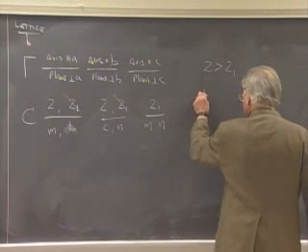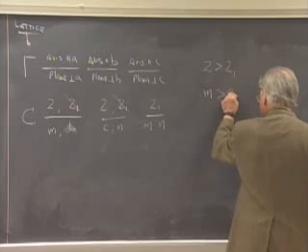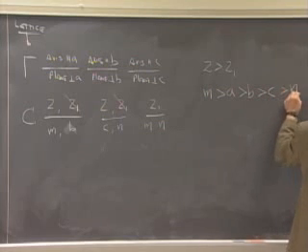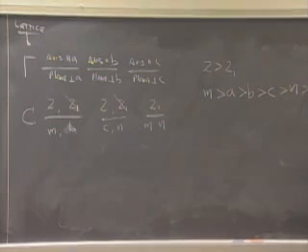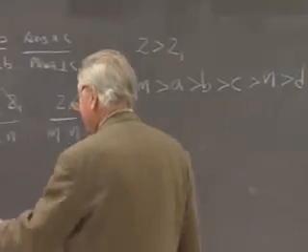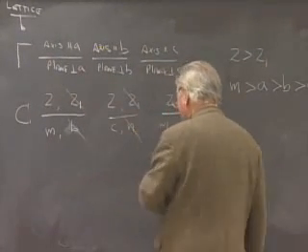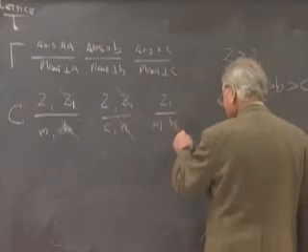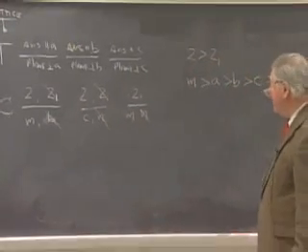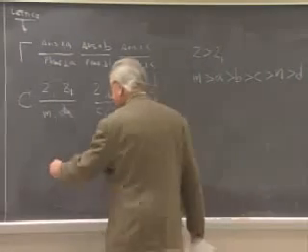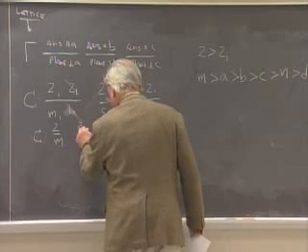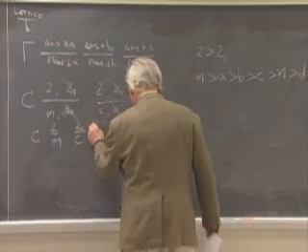For planes, you pick M in preference to an A glide, in preference to a B glide, in preference to a C glide, in preference to a diagonal glide, in preference to a diamond glide, assuming you have a choice of 2 different planes. So in this case, we pick the M in preference to B. Here we've got a C glide and an N glide. We pick the C in preference to the N. And here again, for the plane that is perpendicular to C, we pick the M in preference to the N. So the full symbol would be C 2 over M, C 2 over C, and 2 sub 1 over M.